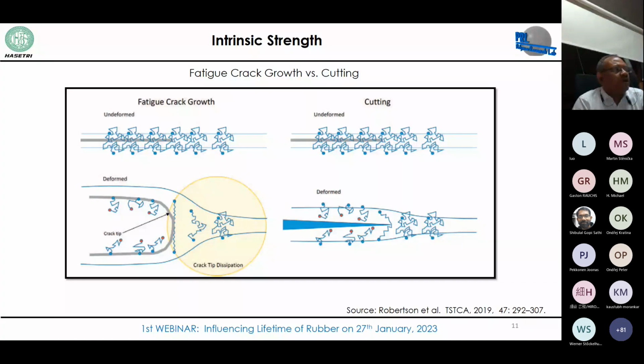However, in the case of cutting, if the dissipation in front of the crack is higher, then it will be difficult to measure the threshold strength. Therefore, one needs to be very careful about the testing procedure, which was also explained in their paper very nicely, and is being used in the present work as well.